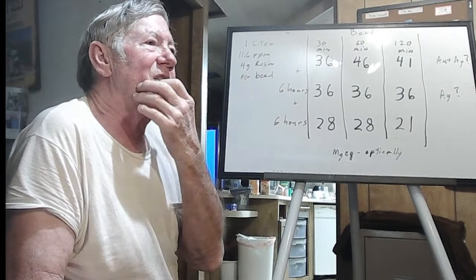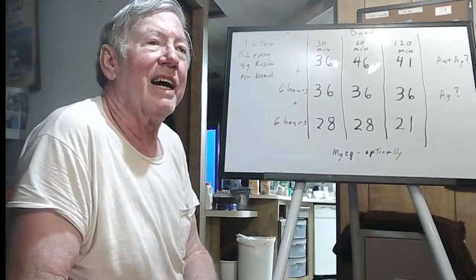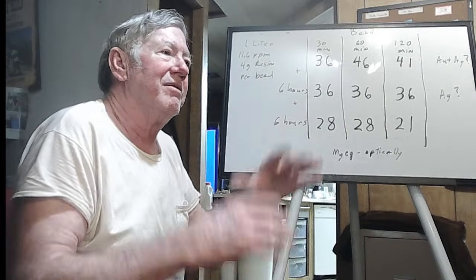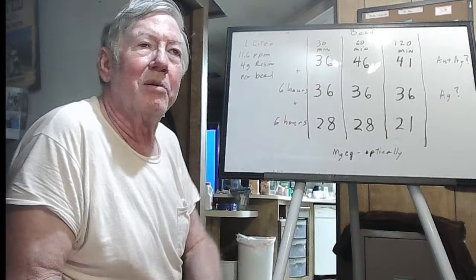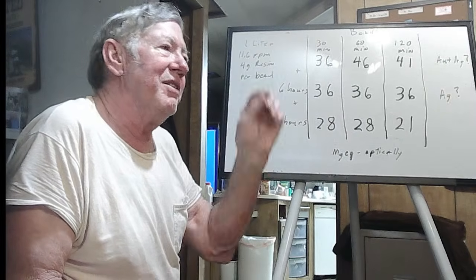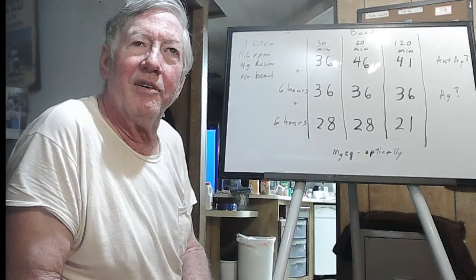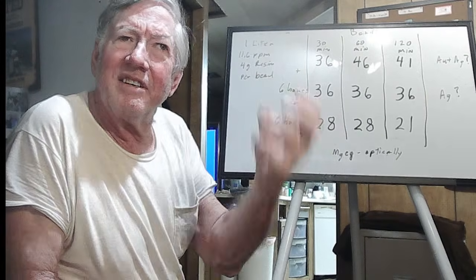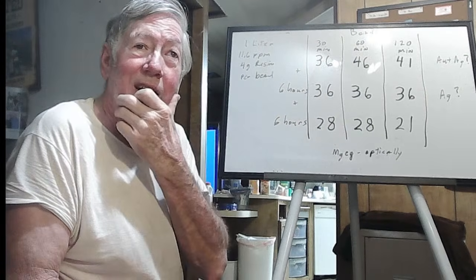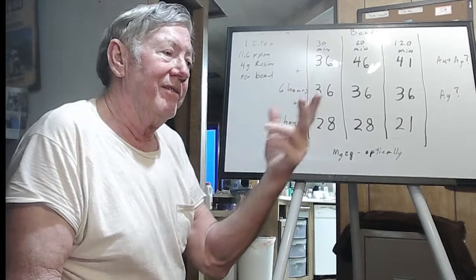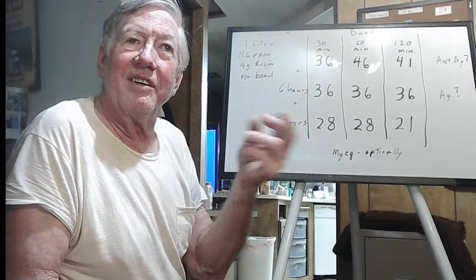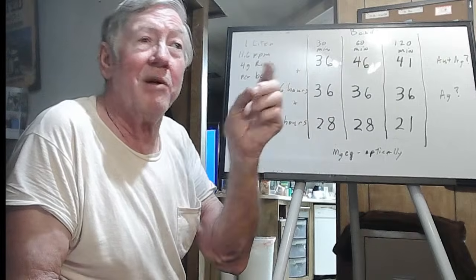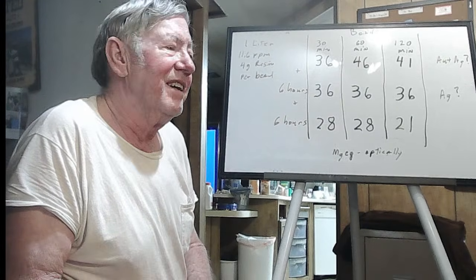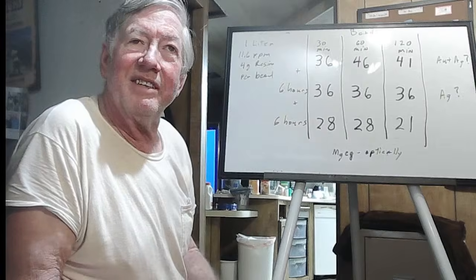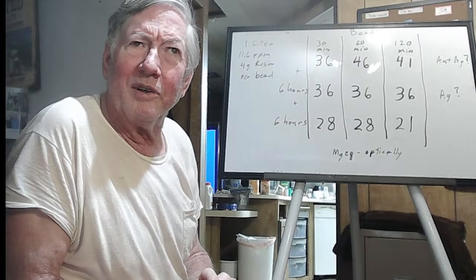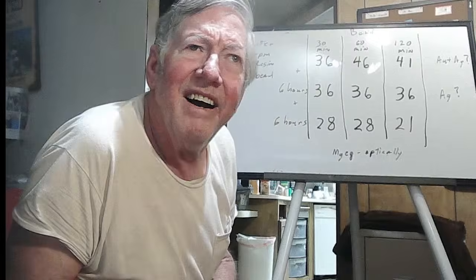Now, Chris Georgie, a while back, did a spreadsheet and printed up a chart to show me, if you have a bead this big of pure gold and it's a sphere of this diameter, how much would it weigh? Now, there's 2 big variables here. Number one, they're never perfectly spherical, although the smaller they are, the better. The other one is how much gold is in it, because it's never pure gold.